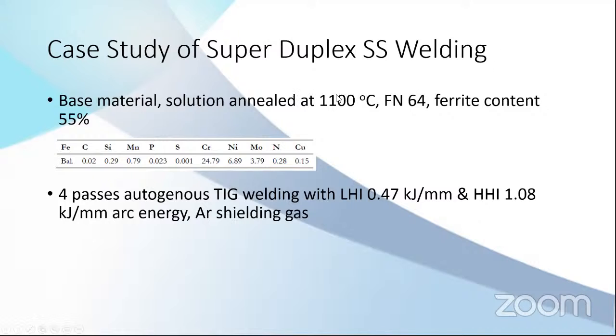It is solution annealed at 1,100 Celsius, so the microstructure is uniform. The ferrite to austenite balance is very good, at 55%. Ferrite number is 64. This is the chemical composition. It's very high in nitrogen, very good. High moly, high nickel. So this is a perfect material. But now we are going to use a 4-pass autogenous weld, with low heat input and high heat input. The shielding gas will be just argon.